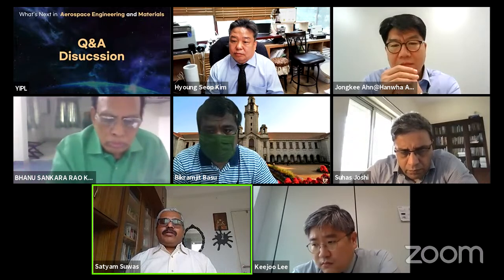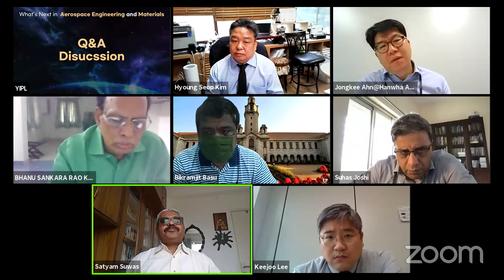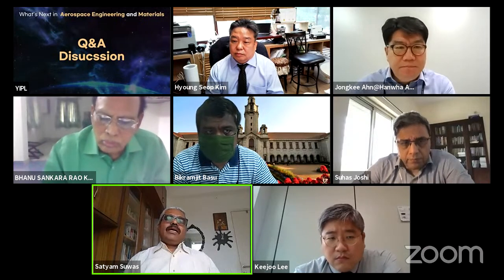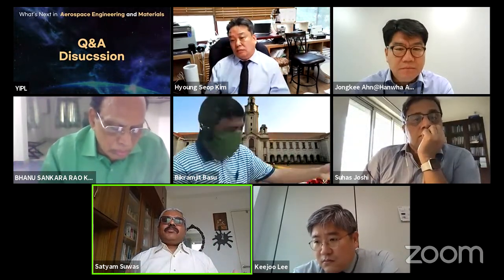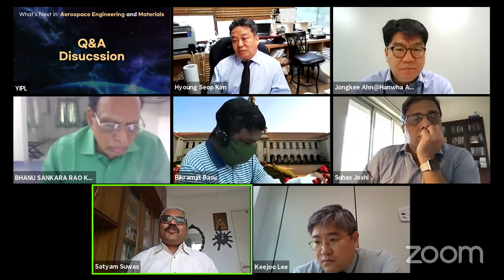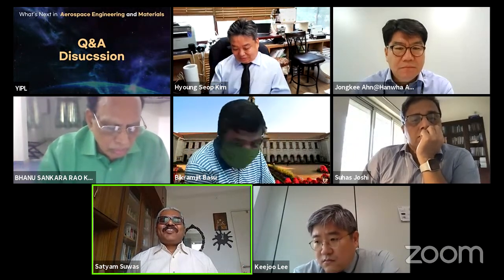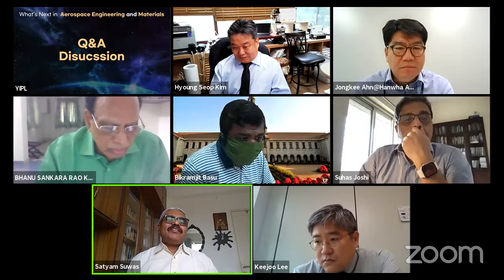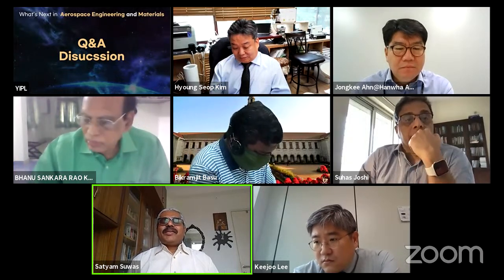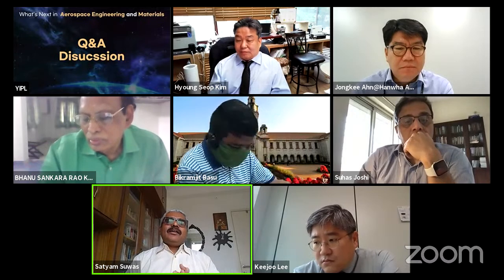And this has been very well proven in our recent paper on 316L, which behaves in a very similar way. Here texture control becomes very difficult, because normally we control texture by plastic deformation and annealing, but here we have no avenue to carry out plastic deformation. We produce near net shape parts. So it is just by a very subtle combination of parameters during printing itself that one has to control it.